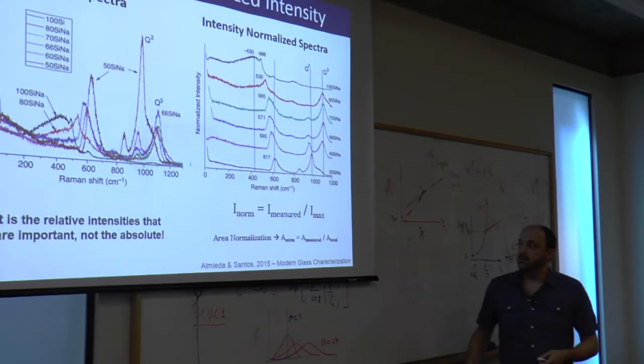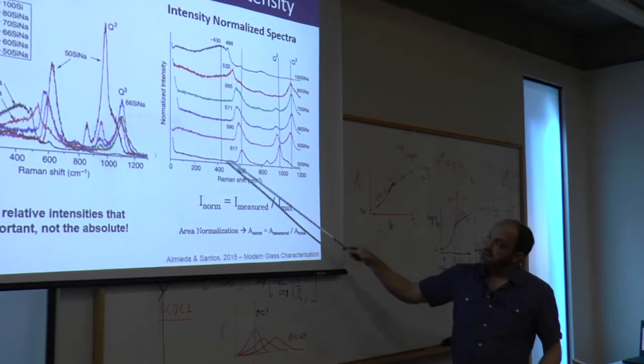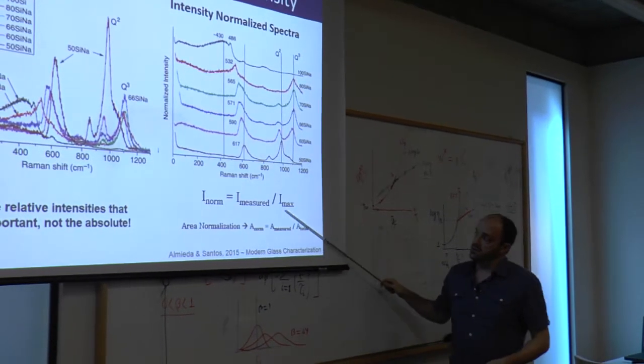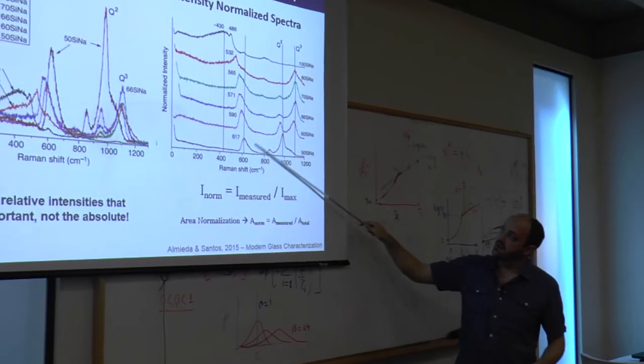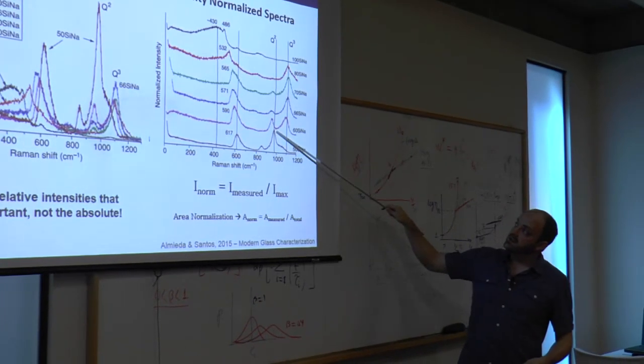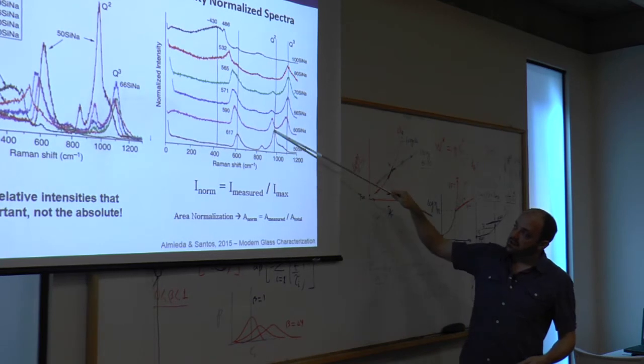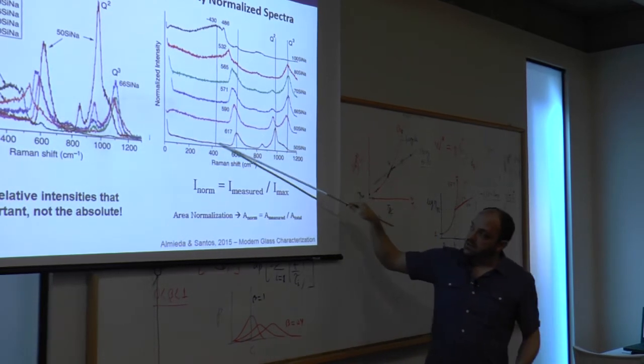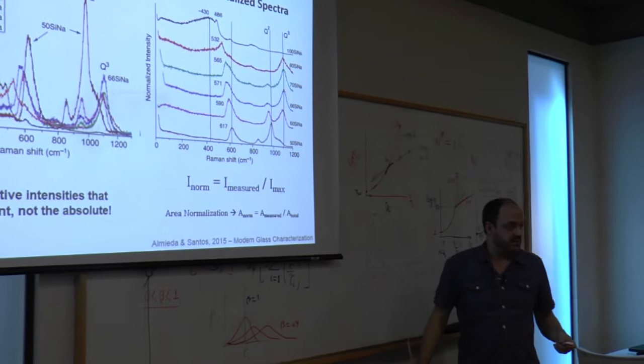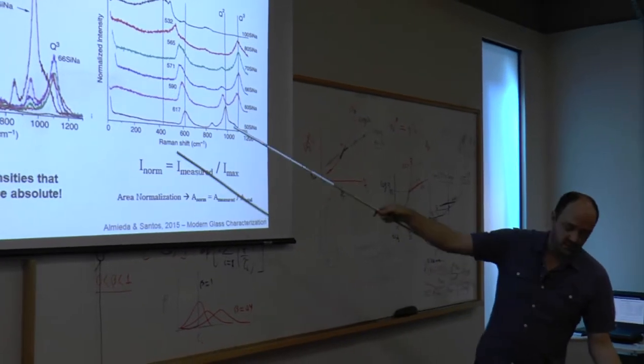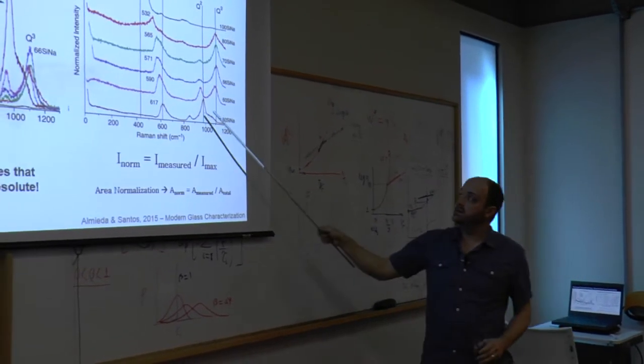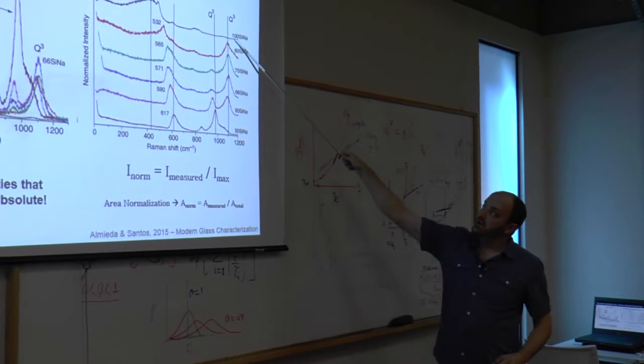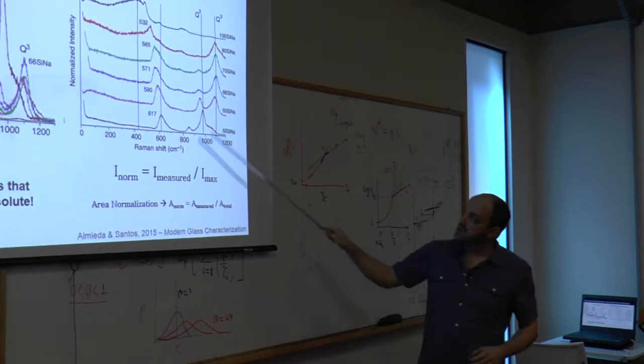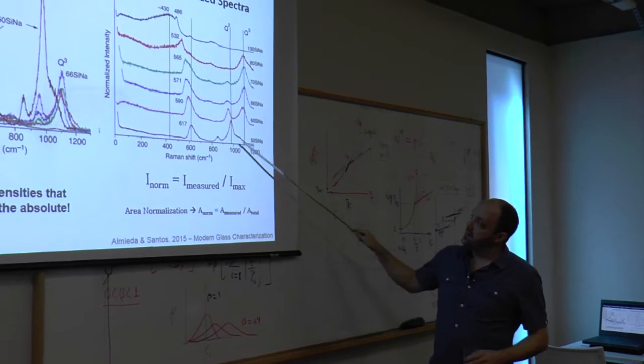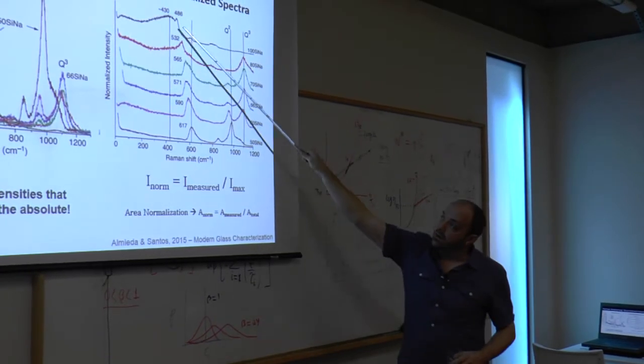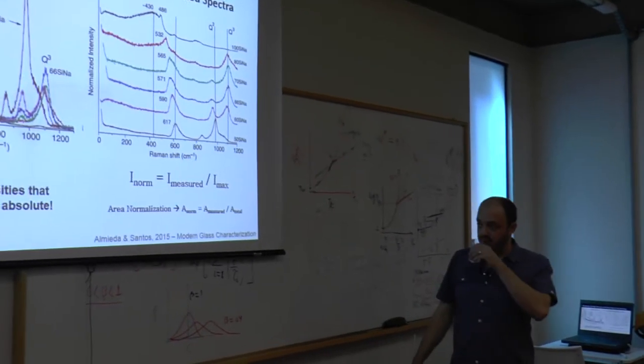The most common is by normalizing the intensity of your spectra to the maximum intensity peak. So whatever your intensity is here, this is the maximum intensity peak, and we make this intensity 1 and make all the other intensities in the spectra relative to that most intense peak. And you can see when you go from the left to the right, you have a much better looking spectra, and you can see that there's clear shifts in where the peaks are at and where they go as you add sodium to the sample.